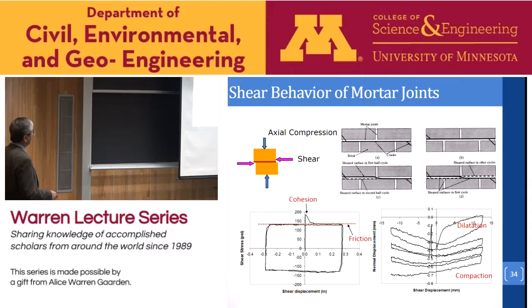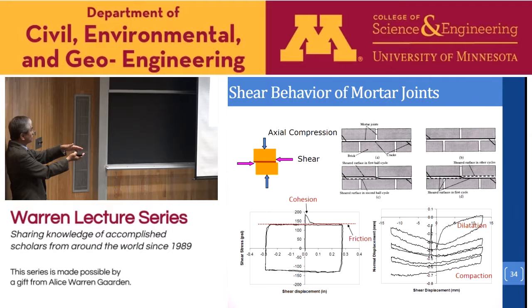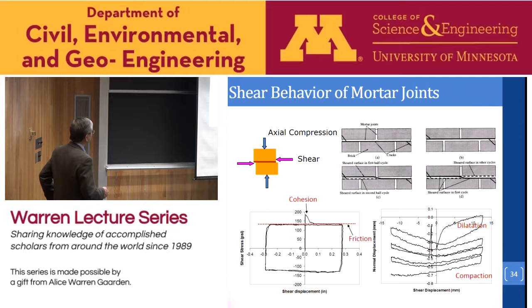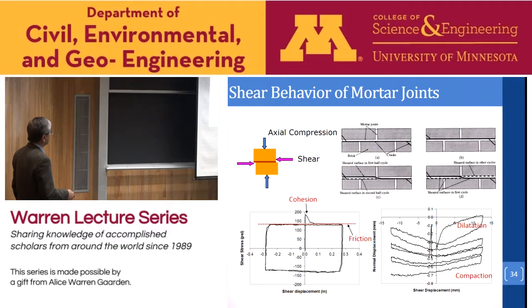And then also we can have some joint displacement in the normal direction of the joint. Okay, so when we slide, sometimes this normal displacement could increase. This is what we call joint dilatation. Joint dilatation is due to the roughness of the joint. When you slide on a rough surface, the roughness, the aggregates, for example, in the concrete, or the roughness in the fracture joint, will force this joint to open. So this is dilatation. But after a few cycles, we can also observe a phenomenon that the joint will have a compaction behavior, mainly because of the damage of the material. The loss of material will cause the compaction.